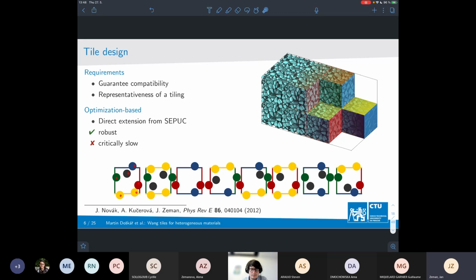So we take as the parameters of the microstructure the positions of individual particles within individual tiles. And what we also need to take into account is that, for instance, if some particle like this one intersects this vertical edge, then the same information must appear in all corresponding edges. If you are generating a periodic cell of your material, this is a constraint you take into account naturally. Here you must do some additional bookkeeping because the periodicity is relaxed, or it can be seen as a kind of multi-periodicity. And once you have your parameterization at hand, you solve an optimization problem and try to match the spatial statistics of your original system by realizations of your microstructures.